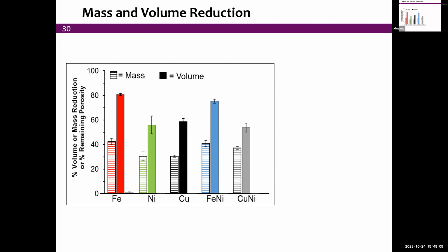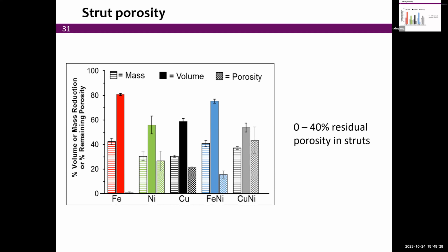Well, we see that for iron, nickel, copper, and their alloys, the weight reduction is anywhere between 30 and 40%, depending on how much polymer we have, and of course, the unavoidable reduction from oxide to metal. Meanwhile, the volume reduction is quite drastic. You saw it with your own eyes, this incredible shrinking. It's as high as 80%, and in other cases, a bit less. When it's less, it's because we have some residual porosity. So really the sum of the shrinkage plus the residual porosity gives you the total shrinkage.